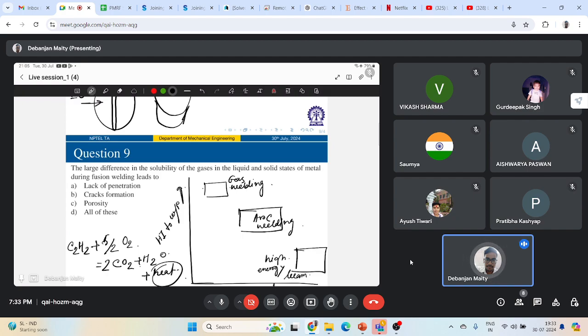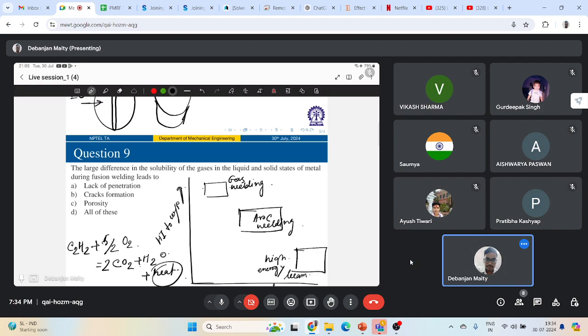So penetration and cracks have nothing to do with the solubility of gas. The gas entrapment will of course lead to porosity in your weld metal. There are other reasons for crack formation or lack of penetration and all those things. Maybe we'll cover them in different lectures. But if you are talking about gas entrapment or a higher concentration of oxygen, nitrogen, hydrogen in your weld metal, you will of course end up with an increased amount of porosity in your weld metal. Okay, so C is true.